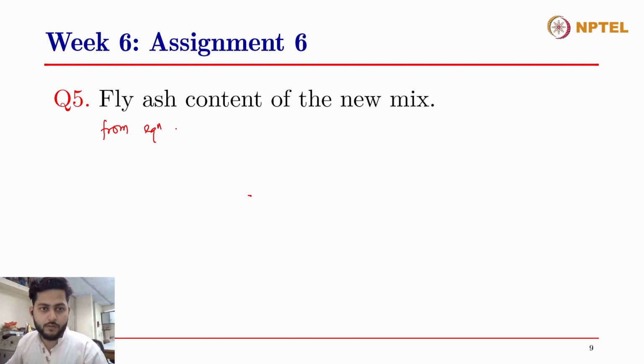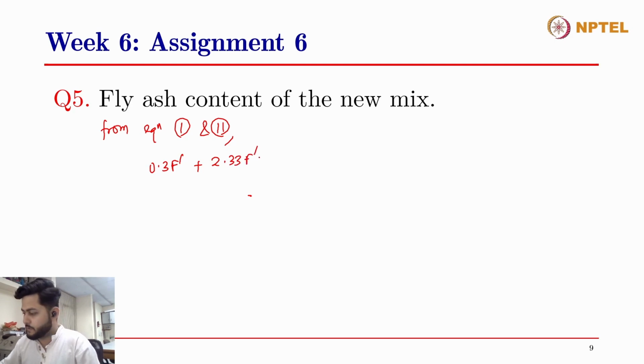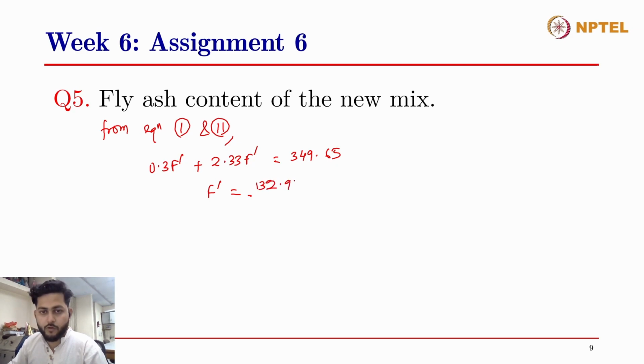From equations 1 and 2, we get that 0.3 times F dash plus 2.33 F dash will give us 349.65, and therefore F dash content will be 132.94 kgs, which can be equal to 133 kgs per meter cube of concrete, right?